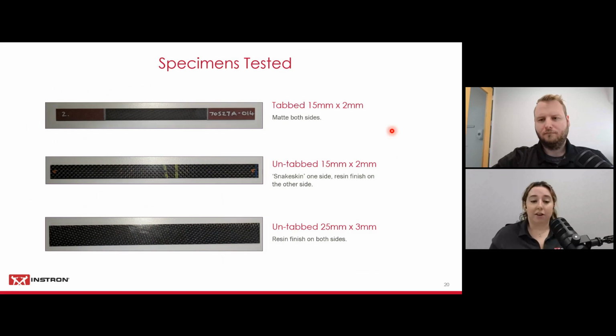The specimens that we have on hand are polymer matrix composites. Again, we don't know exactly what they are, but they were all unique to one another. Our first specimen is a tabbed 15 by 2 millimeter, which had a matte finish on both sides. Our second specimen was untabbed 15 by 2 millimeter. It was a different material. The best way I could describe it is it felt like snake skin on one side where you actually had the exposed fibers, and then a resin finish on the other side. And then lastly, our largest specimen, untabbed at 25 by 3 millimeters with a resin finish on both sides.